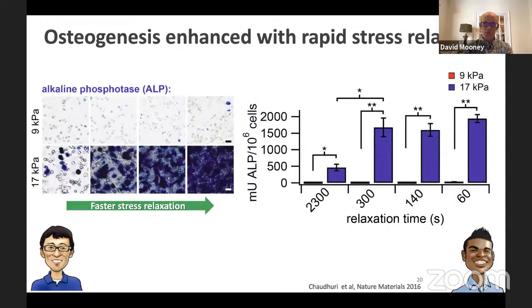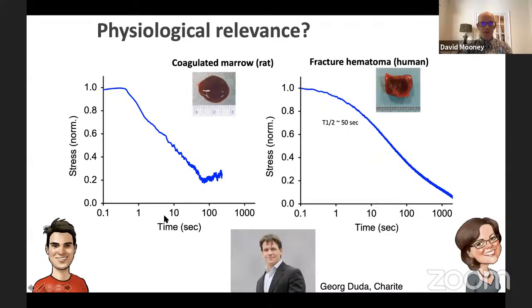Now, the fate of stem cells is also regulated by the relaxation behavior. So here, if we take MSCs and we monitor their ability to become osteoblasts, as indicated by alkaline phosphatase staining, on the left, you can see that if we have too soft of a material, we get very little osteogenic differentiation. If we make a permissive gel in terms of its modulus, we see a very low level of osteogenesis if the gel is too elastic, but as it becomes more and more viscoelastic, we get greater and greater osteogenesis, as indicated here by ALP staining. And actually, we see the opposite behavior for adipogenesis, that basic adipogenesis is favored by more elastic materials versus viscoelastic materials. Now, one of the questions that may arise is whether this really has any physiological relevance, or whether it's just some parlor trick that we've developed with these materials.